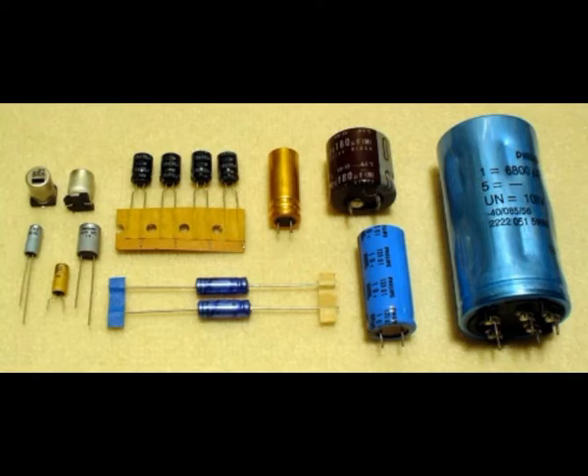Solid electrolytes' leakage current drops much faster than in the case of non-solid types, but it remains at a somewhat higher level. Wet electrolytic capacitors with high water content electrolytes in the first minutes generally have higher leakage current than those with organic electrolyte, but after several minutes they reach the same level. Although the leakage current of electrolytic capacitors is higher compared with the current flow over the insulation resistance at ceramic or film capacitors, the self-discharge of modern non-solid electrolytic capacitors can take several weeks.